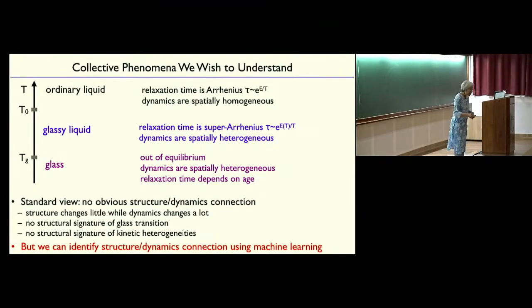So the standard picture, and by 2010 it was even enshrined in a book called Dynamical Heterogeneities in Glasses that came out of a workshop in Leiden, is that there was no real connection between structure and dynamics. The evidence for it was, for example, that the structure changes very little, while the dynamics can change by many orders of magnitude. People had searched for probably 5 decades by then and found no structural signature of the glass transition and no structural signature of kinetic heterogeneities, which I'm going to mention shortly.